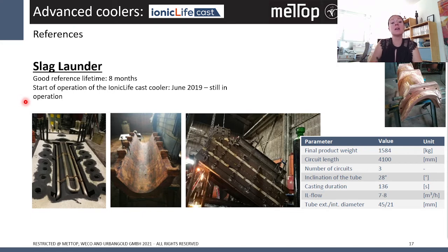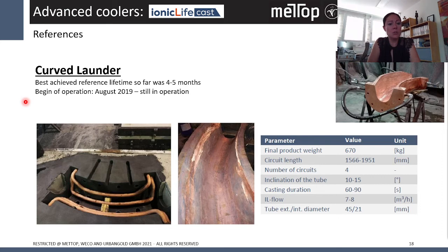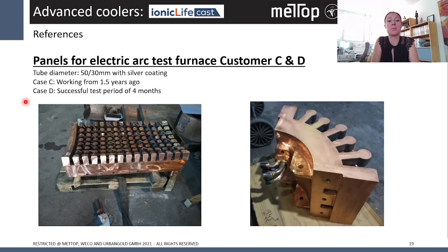And I have to say it is still in operation, so it's more than 2 years now with one slag launder, which is very, very nice. Actually, it's not so nice for us, because we don't sell as many launders as we want to, but for the customer, it's a perfect result. 2 years of operation for a launder. Also, this is a curved launder. This is also in operation almost 2 years, where the prognosed lifetime was only 4 to 5 months. So also a very nice result for our customer.